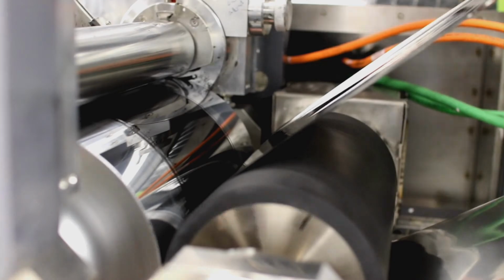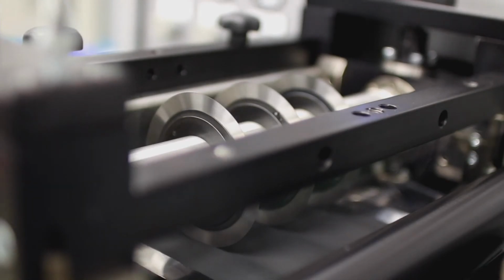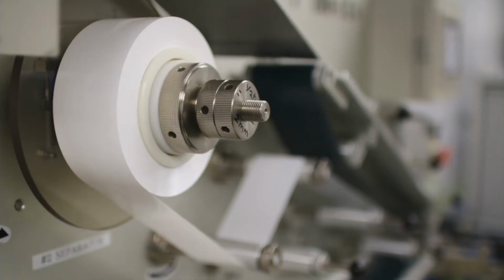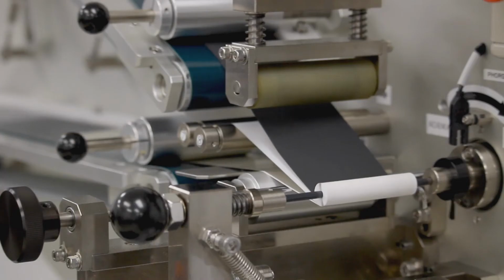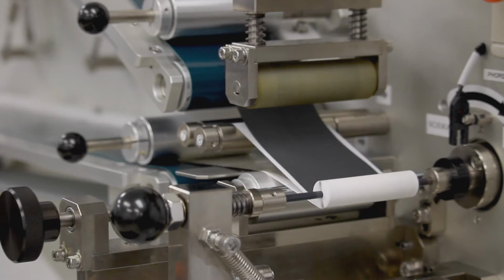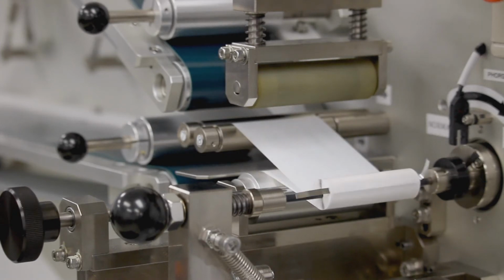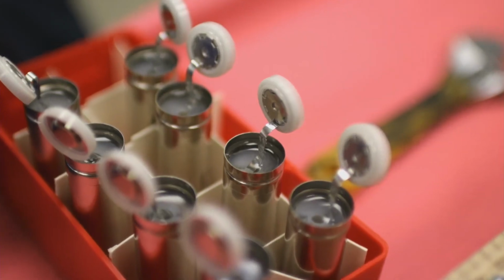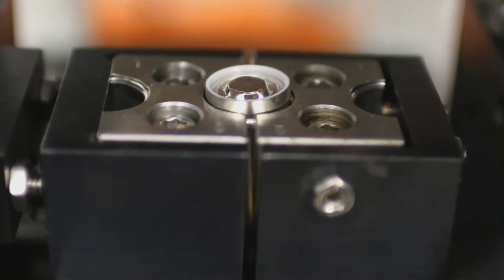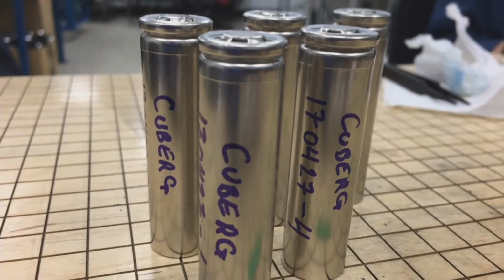So this is some shots of some of the processing that we do, all roll-to-roll processes for electrode coatings and slitting. And you actually see the cell winding process with separator, lithium metal, and cathode going into the jelly roll. This is in typical 18650 format cell that we made about a year ago. Electrolyte fill and sealing process, all pretty standard and pretty easily scalable when you start thinking about actually using this for actual practical applications. And so we continue making prototypes. We currently have both cylindrical and pouch cell prototypes, and especially on the pouch cell side, seeing very, very good specific energy and performance out of these cells.